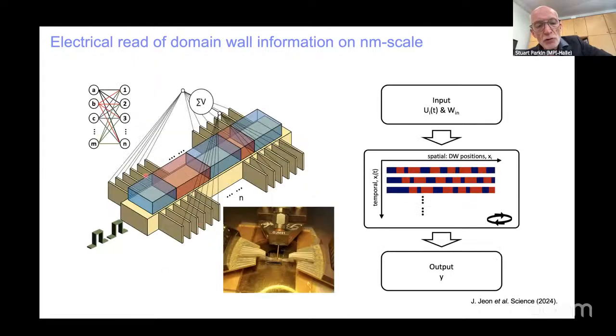Depending upon the ratio of the width of the magnetic layer compared to the platinum layer, if we make the platinum wider, the Hall voltage will detect the magnetization from a further distance from the Hall electrodes. And this is very important because it enables us to detect one domain wall anywhere along the racetrack by proper design of the width of the extension of the platinum electrode.